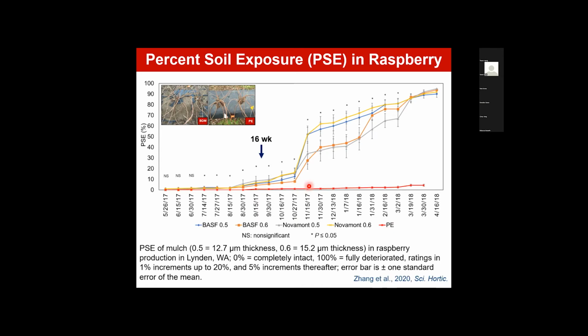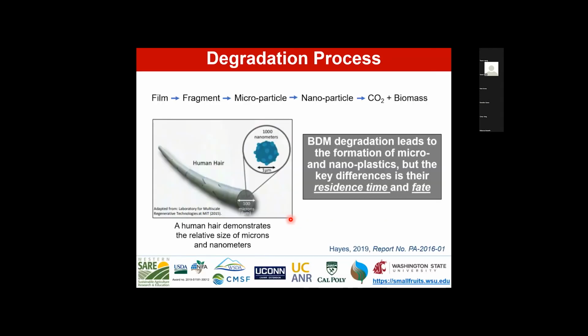So you can see polyethylene had very little percent soil exposure, which is expected. And then likewise, it was expected that the biodegradable plastic mulches would deteriorate over time. And this is usually a longer period that they're deployed. We're testing these in perennial crops in my program, but we see similar results when we look at annual crops and percent soil exposure in those systems as well. So the degradation process too is something important to consider.